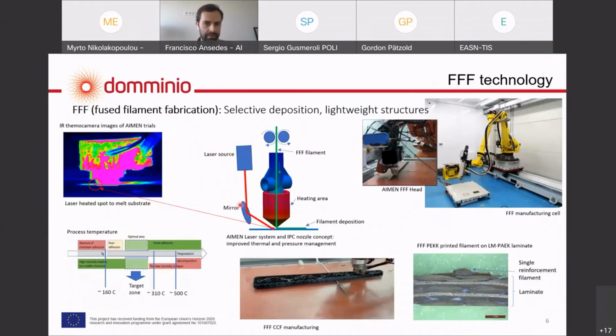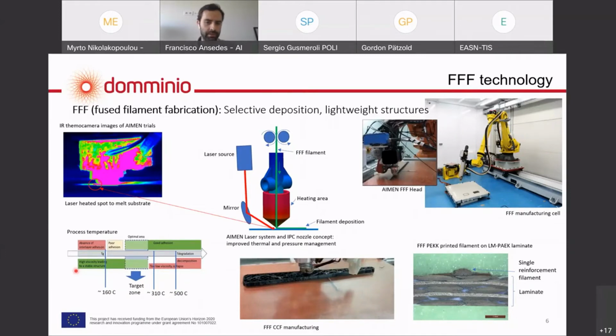FFF is fused filament fabrication, where we deposit a filament that we feed through a printing head, and it gets heated in the nozzle that you can see here and is finally deposited on the substrate. For this, IPC is developing an innovative nozzle concept that controls the temperature and the pressure inside the nozzle, so we can achieve good properties. We are also installing a laser source heating system to heat up the substrate. This is in order to work in an optimal temperature area and to have the substrate in a molten state, to melt the substrates so we have a good consolidation and adhesion between the substrate and the molten filament being deposited.